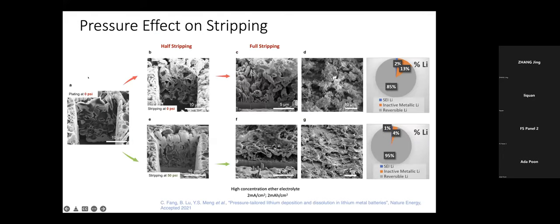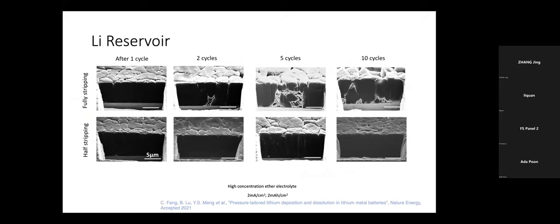You can do the same interesting experiment with the carbonate electrolyte. So you deposit some kind of very porous structure, and then you start stripping, and the stack pressure still has a very huge impact on the reversibility of the stripping. So the lesson here really shows us that lithium metal needs pressure control during the deposition and the stripping. And you can do all sorts of interesting experiments to showcase where the weaker spot is. Obviously, I think by intuition, many people could think that the current collector, copper and lithium, the interface is the weak spot. And we can show proof that this is the case.